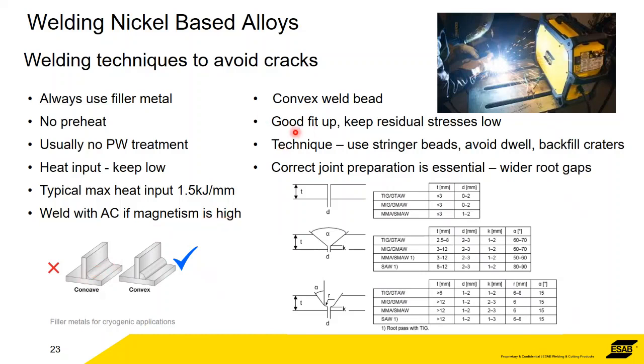Obviously, part of that is a good fit up. If you have lots of residual stress in here at the fit up, then these alloys don't lend themselves to holding everything together without problems. So keep residual stresses low and use a convex weld bead.